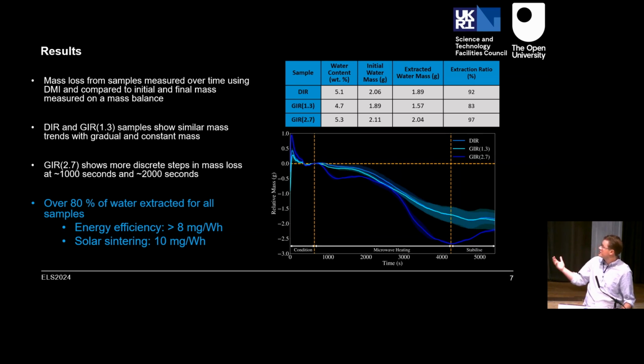Now, as I mentioned already, about 80% of the water was extracted for all samples, which gives you an energy efficiency of 8 milligrams per watt hour, which compared to other solar sintering experiments is kind of comparable. Now, obviously, solar sintering is using free energy, it's not using any energy sources, but there are advantages to using microwave heating. The scalability should be quite good, and the reliability of using it should be quite good as well.